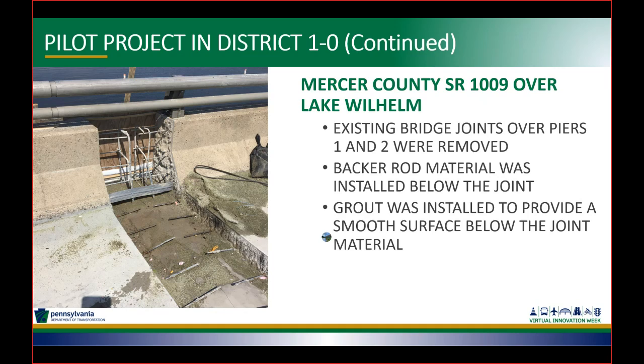A backer rod material had to be installed down in between the two slabs and the old joint to prevent anything from leaching down through. A grout material was also placed there as well to provide a smooth surface to pour the link slab material on. It also acts as a debonding zone, which I'll show you more about in a future slide.